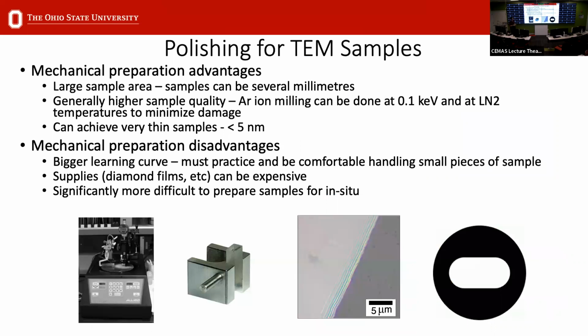Polishing for TEM samples is usually a little bit more challenging for a lot of people because it requires more dexterity, and you have to monitor your sample thickness as you polish it. Typically you would use a tripod like you would for the SEM. You would cut your sample down, generally on the order of a millimeter or two, polish one side down with progressively finer grits, and then something like colloidal silica, flip it, and do the same thing again. In this case, you want to get your sample down under 100 microns thick, which you would then monitor under an optical microscope when you're trying to get this precisely thin.